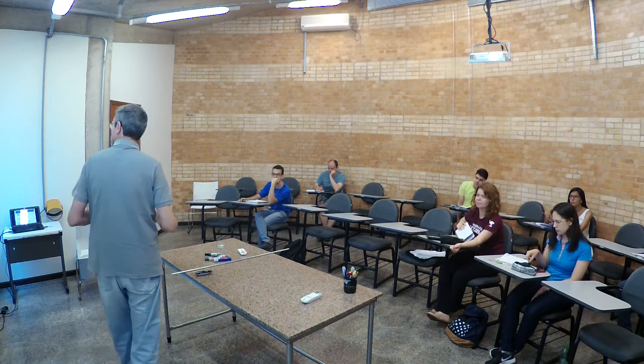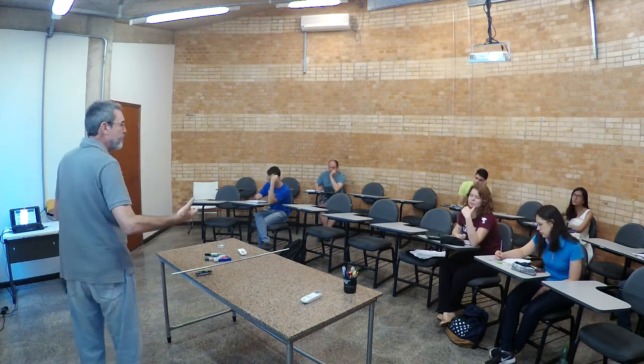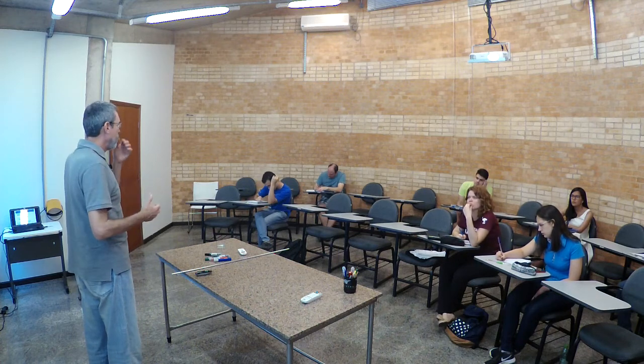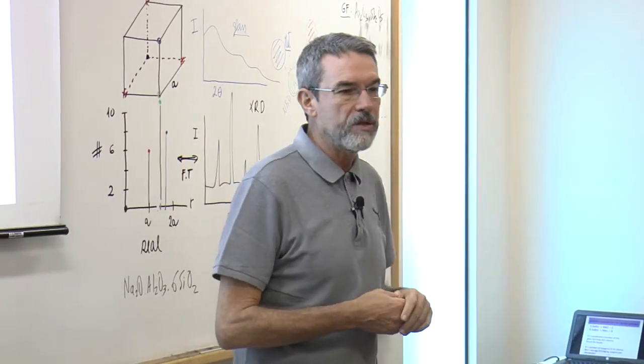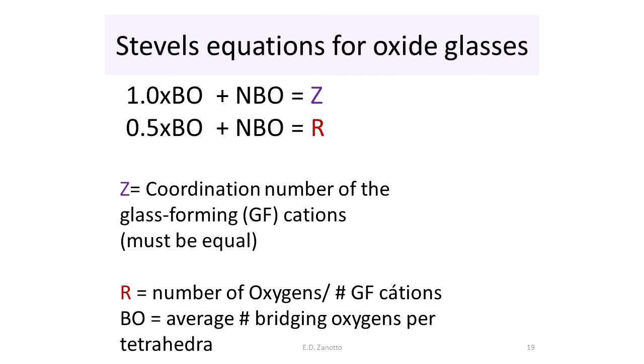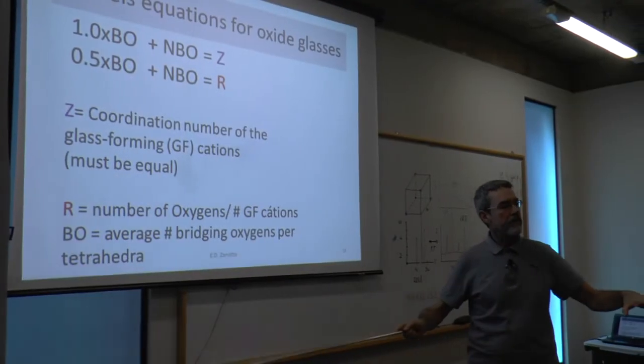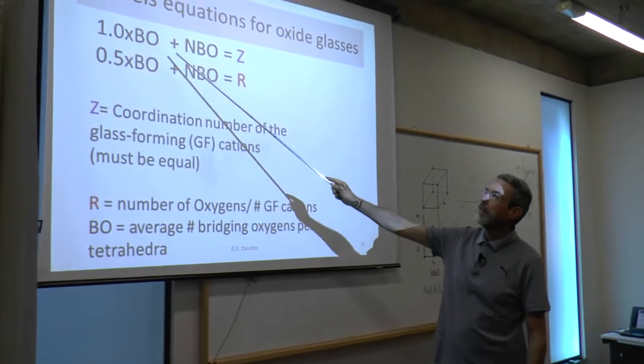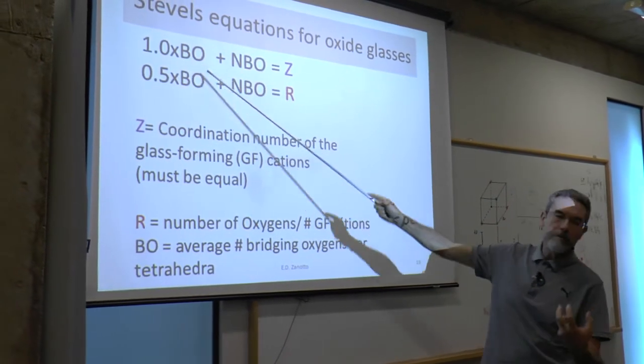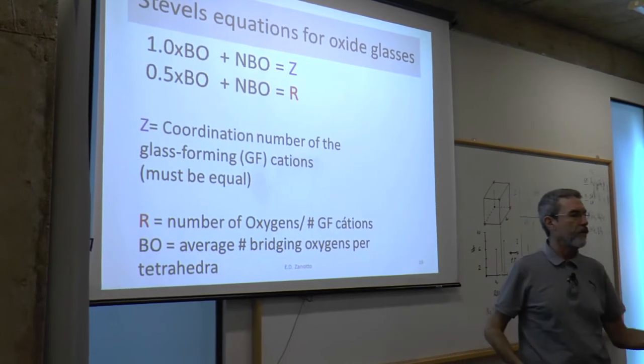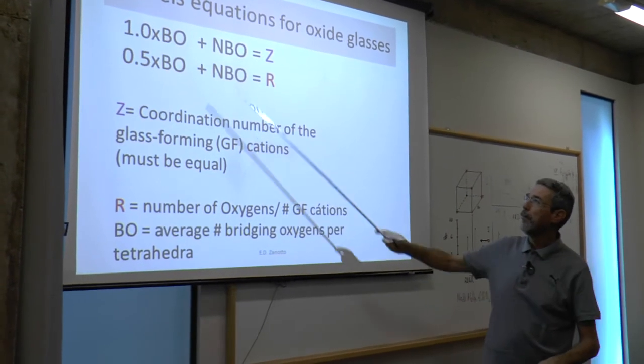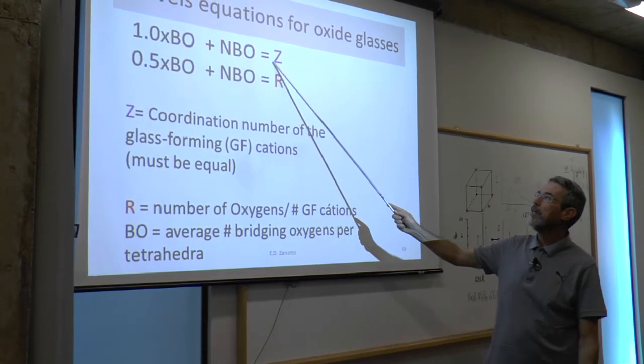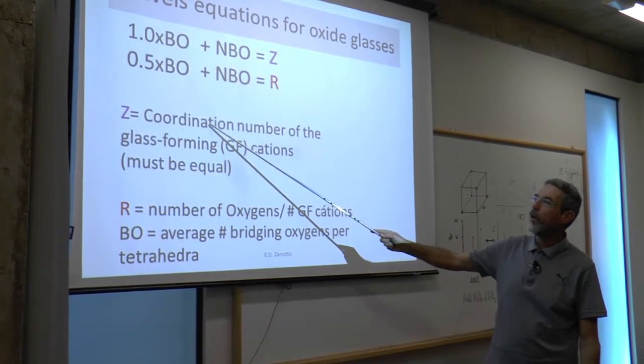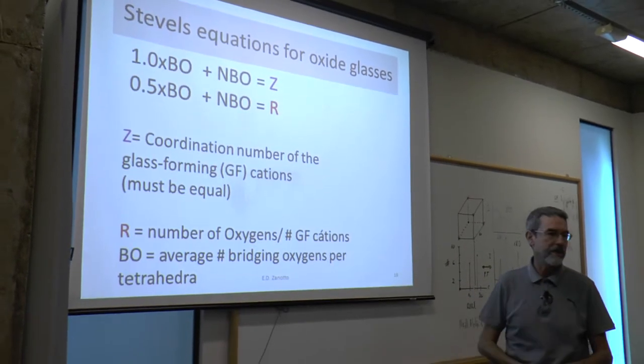Now I'm talking about bridging, non-bridging oxygens, bridging, non-bridging. Let's do an exercise. I'll give you 3 minutes. This researcher, Stevels, came up with a very simple formula. If you take any glass composition and calculate the average number of bridging oxygens per tetrahedron, it's always per tetrahedron, plus the number of non-bridging oxygen is equal to Z, where Z is the coordination number of the glass-forming cation.